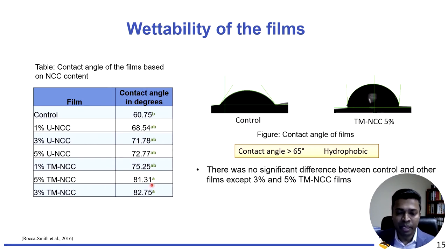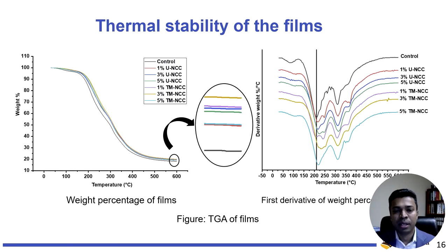So when we add the nanocrystalline cellulose, as you can see in this chart, especially at 3% and 5% addition levels of oxidized nanomaterial, there is a significant improvement in the surface hydrophobicity of the films that we prepared. So this is one of the better advantages when it comes to biopolymer-based plastic materials.